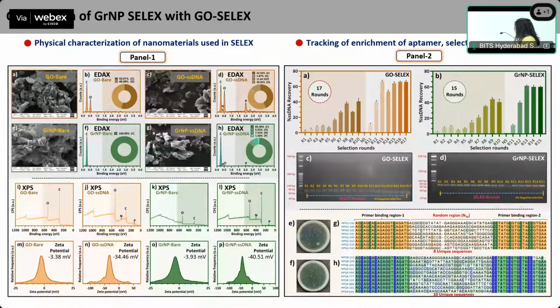Further, XPS was also done with both materials, before and after ssDNA, to see the binding energies, and zeta potential also gives us an impression that the ssDNA is efficiently adsorbed onto the material surface. Then he carried out the SELEX rounds. Here you can see it has been reduced tremendously to 15 or 17 rounds. In the case of GO SELEX it was 17 rounds, and in the case of GRNP SELEX it was 15 rounds.